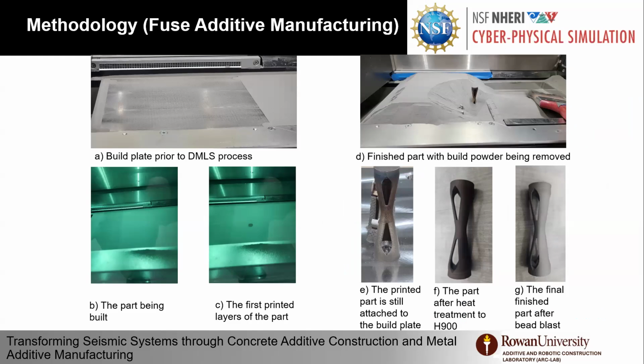So the process itself starts with preparing the build plate for the DMLS process, using the powder that we use, 17-4 PH stainless steel, and the laser continuously going layer after layer. As you can see here, this small dot in the second figure from the left on the bottom side shows you a solid dot, which is actually the outside circle perimeter of the bottom and top side of the double funnel.